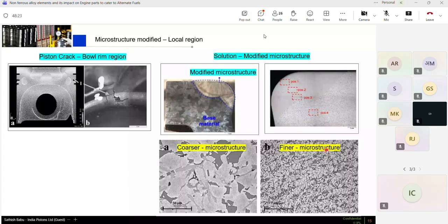So what the current trend is today is that a normal aluminum alloy cast with gravity casting will have a very coarse microstructure. You can see here the silicon particles spread across. And typically, on the left-hand side here, the piston as a part is subjected to very high thermal load. This portion we call the bowl rim region, where it is subjected to very high thermal load and mechanical load. This part is very quickly prone to fatigue crack. So in order to avoid this kind of issue in alternate fuels like hydrogen, despite the high heat release rate, we use a technology called a cooling gallery inside.